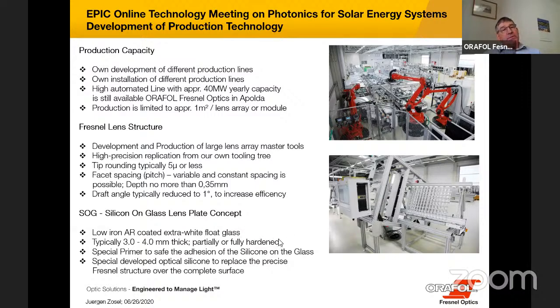We also did develop a lot with our partner in the glass industry to have the right glass, because we had to use an AR-coated glass, which is adapted not just for the visible range of a lens. It also has to work in the UV and in the infrared range, because this is the very special width of.